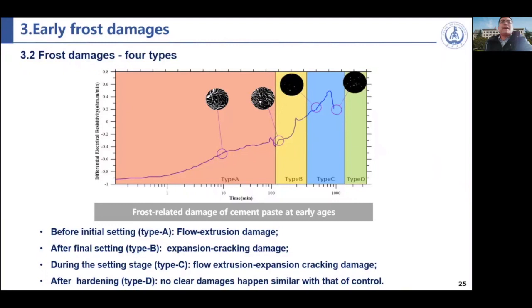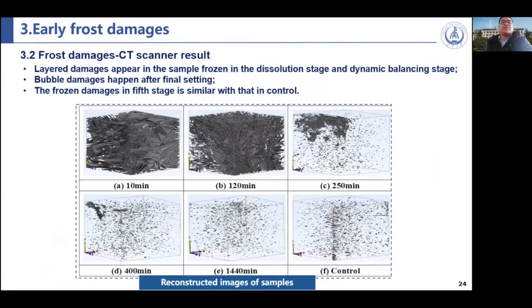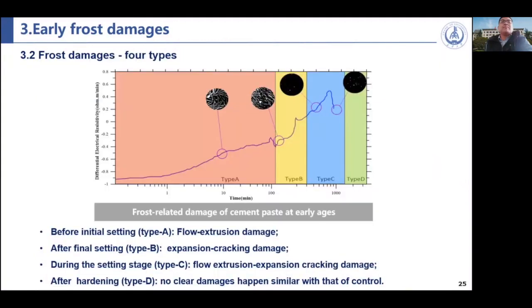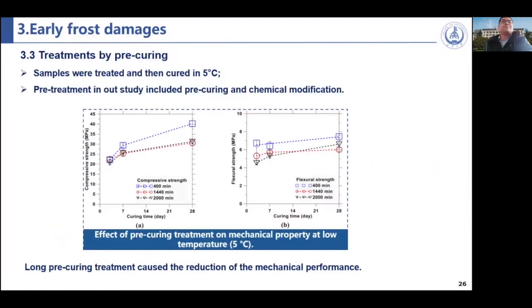And after hardening, we call it type D. In this part, the strength behavior and the performance are similar to that of the control sample, and we also found the structure of the sample is similar to the control sample. So we call it type D. There's no difference, or the difference is very small compared with the control sample.